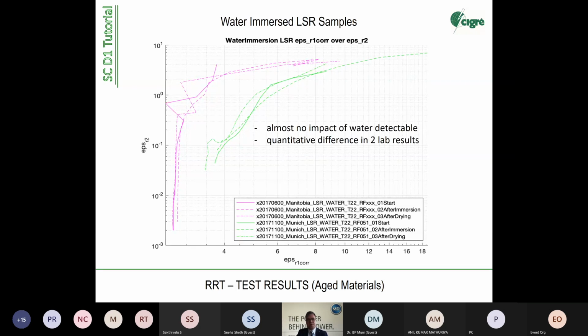these two different labs. The pink one is Canada, the green one is Munich. You see more or less the same, and here you see the start, after immersion, after drying. So more or less they are in the same range, and water seems not to affect the liquid silicone rubber material so much. This difference between the green and the pink one, it's a difference, or it's still the error that we make with the test method.